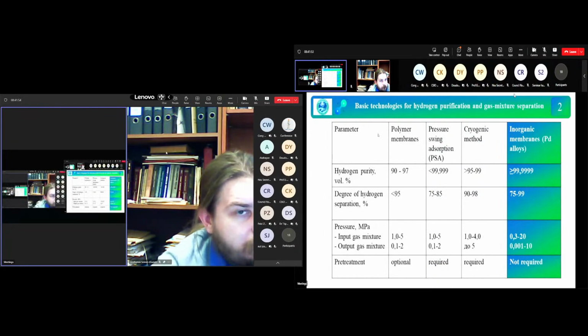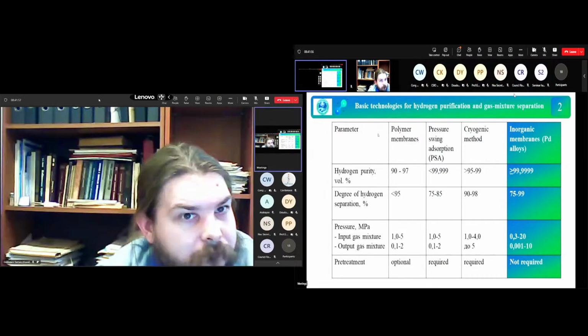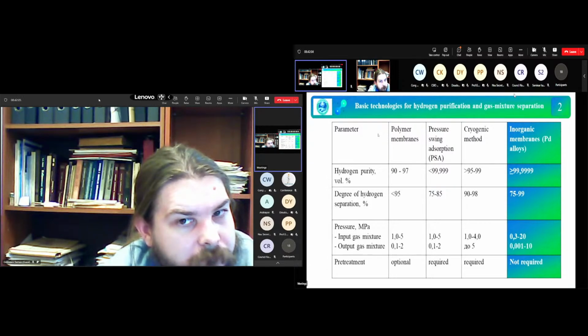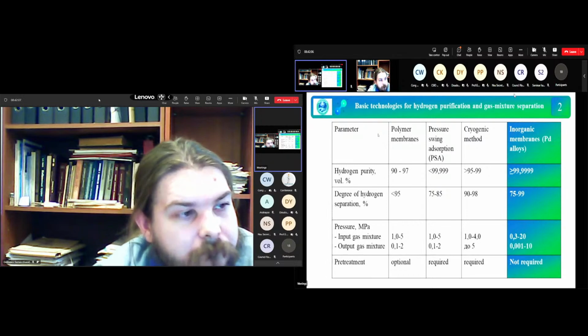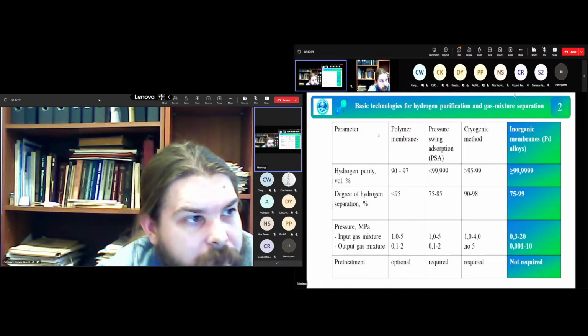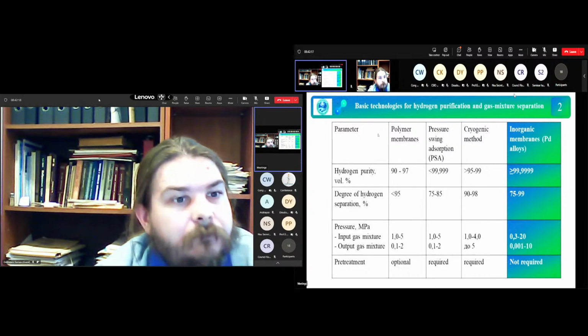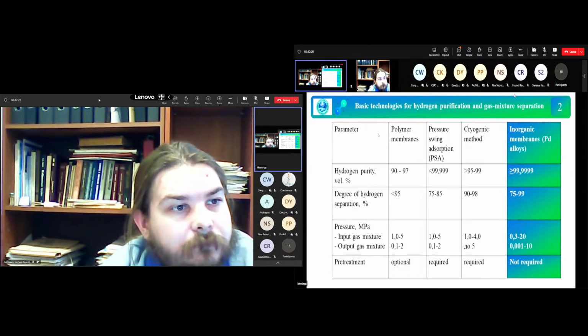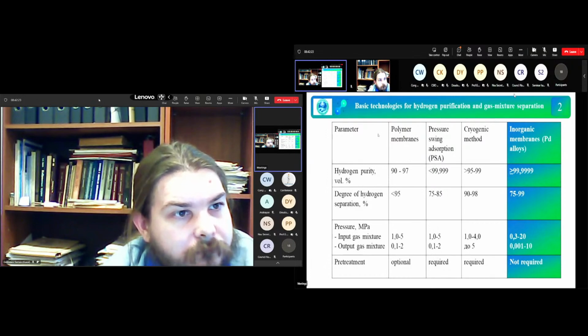The single technology which is both more cost-effective and most productive is the separation of hydrogen by its selective diffusion through metallic membranes made from special palladium-based alloys. This is the hydrogen membrane technology that makes it possible to produce high-purity hydrogen. The volume hydrogen content is more than 6N9. This separation method is single-stage, simple, reliable in operation, sustainable, and does not call for a preliminary hydrogen purification.